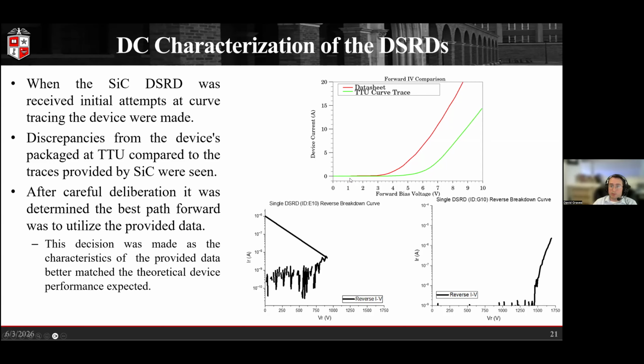But in our device, we ended up with slightly different results that we ended up wanting to empirically match. One of the other things to note with this is we were given bare die devices. So we'll see an image of the actual die here in a minute. But that became somewhat of a challenge for us. We can see in some of the reverse breakdown curves, we were not able to accurately characterize it in reverse bias because the device would break down prematurely. And that was even with various mitigation techniques, like putting the entire device inside a bath of Fluorinert to prevent breakdown around the device.